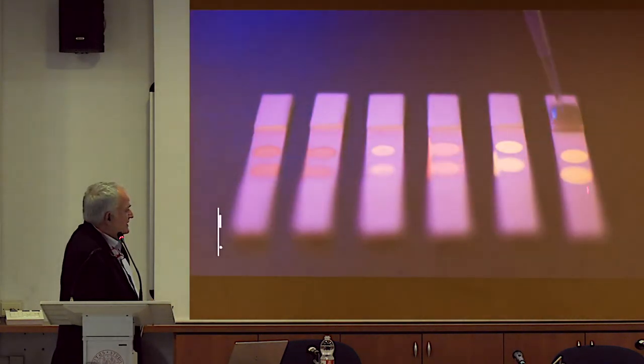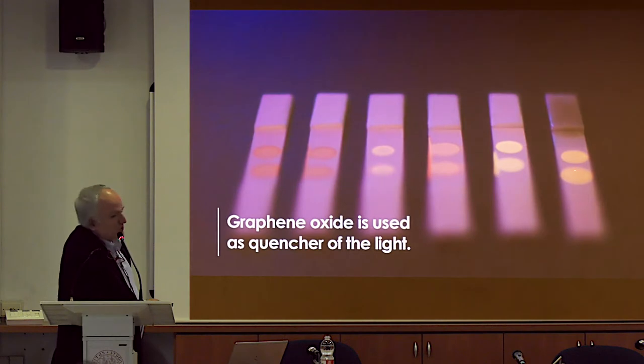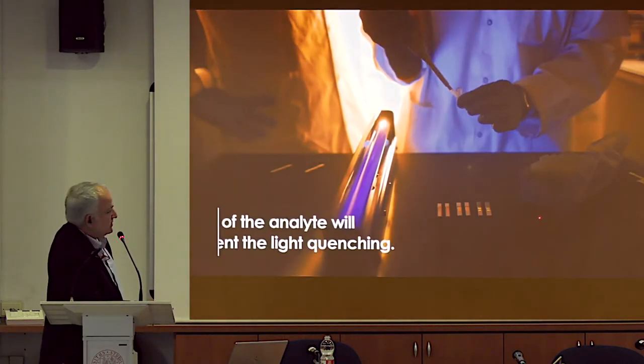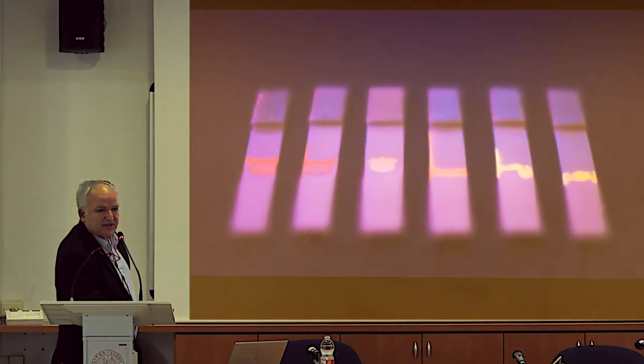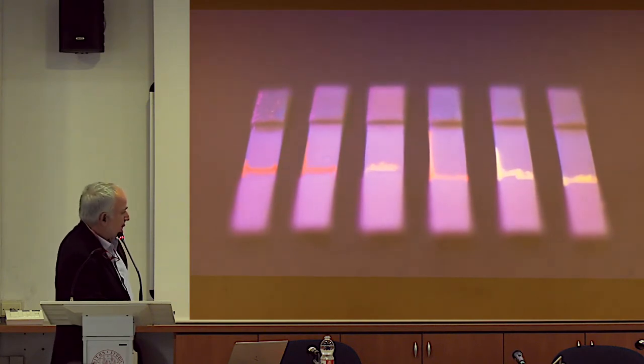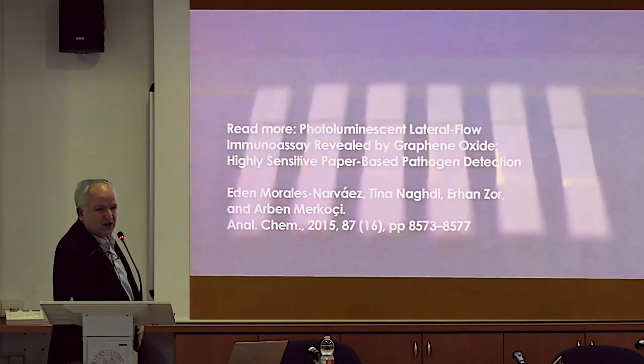So now you see that this photoluminescence of quantum dots is quenched in the presence of graphene oxide. So this is really a very simple application, but very efficient, where the graphene oxide is used to reveal this bacteria in this case, but we can adapt this for any kind of application just by changing the receptor. So we correlate also here the change of the color, the photoluminescence, with the concentration of the analyte we want to detect. And finally, I am just moving to the last thing I wanted to show you, which is the stamping of graphene.